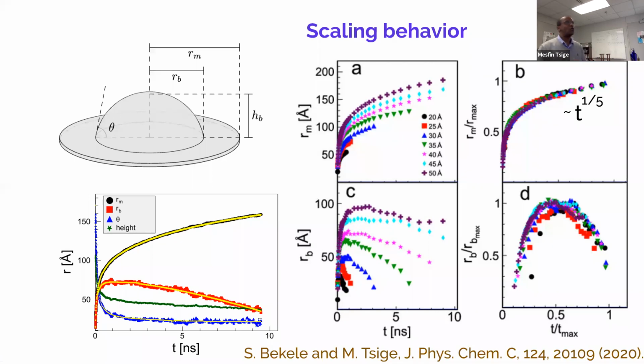When we look at the monolayer radius as a function of time, of course, there will be dependence on the droplet size. We can actually come up with a universal behavior when we normalize that monolayer radius by the maximum monolayer radius. The maximum means when the droplet completely wets the surface, when it just becomes a complete monolayer. We call it R max, and the time it takes to reach that point. We get this universal behavior, independent of our droplet size. And what we have observed is that this scales as t to the power of 1/5 at a later stage. This is very different from what has been predicted by theory, usually known as Tanner's law. Tanner's law says that at a later stage, it should grow as t to the power of 1/10. What we have observed in our case is much faster dynamics.